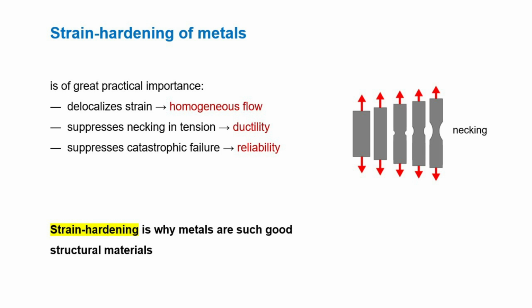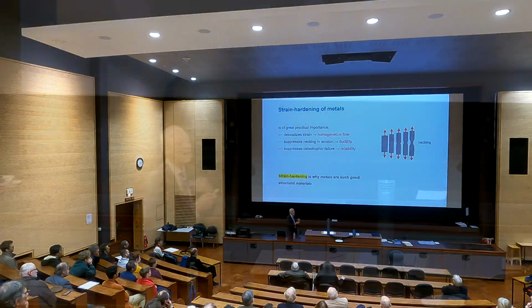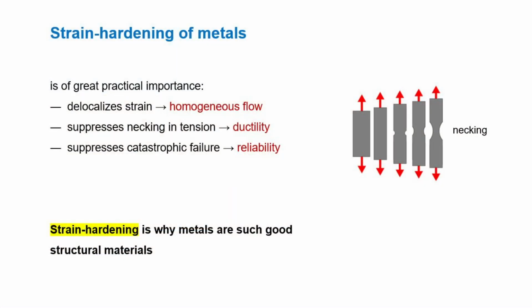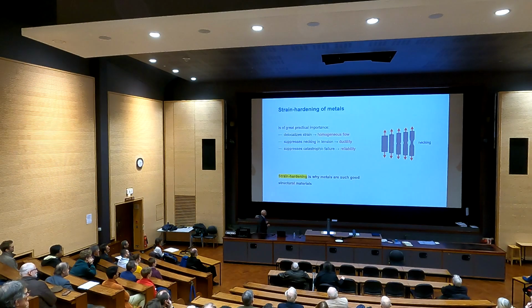And that would be, well, once the material starts to get thinner, if it didn't harden enough, it would continue to get thinner. You would call that necking, and the material will rapidly fail. It won't allow you to go to that 30%. The reason you can go to the 30% is that if it started to get a bit thinner, it doesn't just get thinner, it also gets harder. So it protects the material from further flow there, which forces the flow to spread through the whole bar, which is why you get the uniform flow and the ultimate extension.